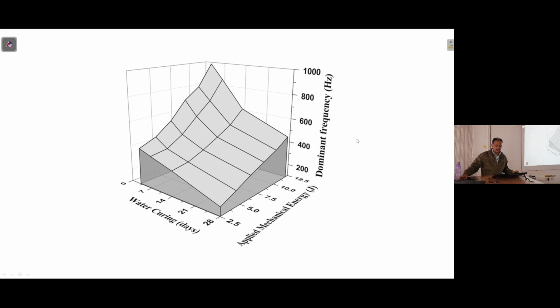And also the variation of dominant frequency you can see here. For this we did fast Fourier transformation of the signals we obtained, and then we obtained the dominant frequency. That could also be an important parameter for the measurement, because depending on different frequency ranges you need different kinds of antenna if you want to increase the distance and so on, right? So this shows that variation.